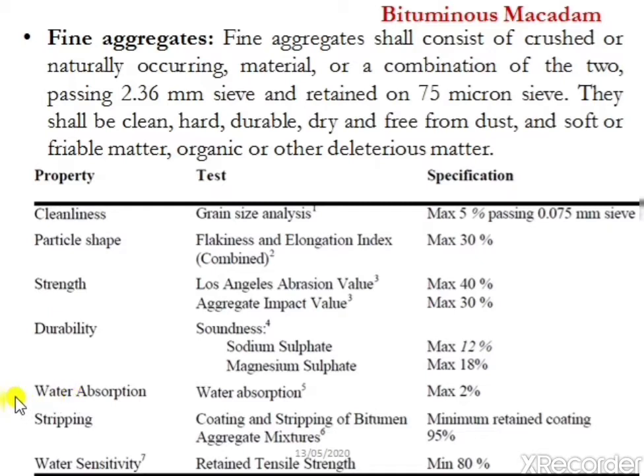The next test is the stripping test, that is, the coating and stripping of bitumen aggregate mixtures. Here the minimum retaining coating should be 95%. The stripping value of aggregate is determined as the ratio of uncovered area observed visually to the total area of aggregates, expressed as a percentage. Bitumen and tar adhere well to all normal types of aggregates provided they are dry and are not exceptionally dusty.